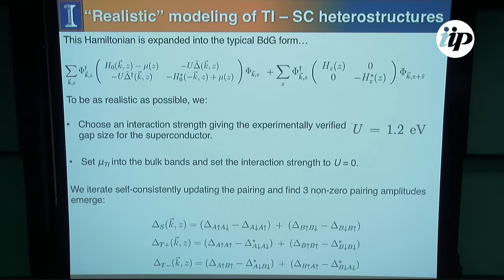So what this is simply: I have a singlet component, which I would expect because I have proximity coupling from S-wave superconductivity. And then I have 2 triplet components, and I expect these because I haven't broken time reversal symmetry. So I would expect there not to be one over the other. I would expect there to be both of these.